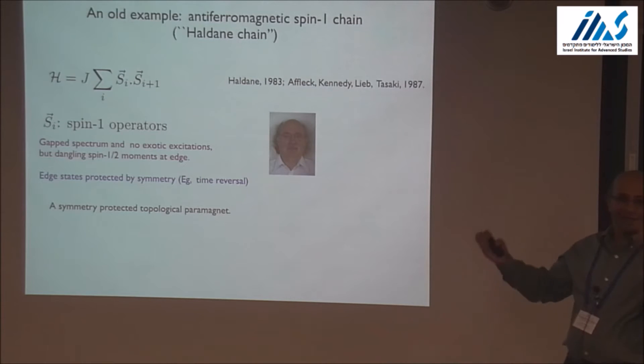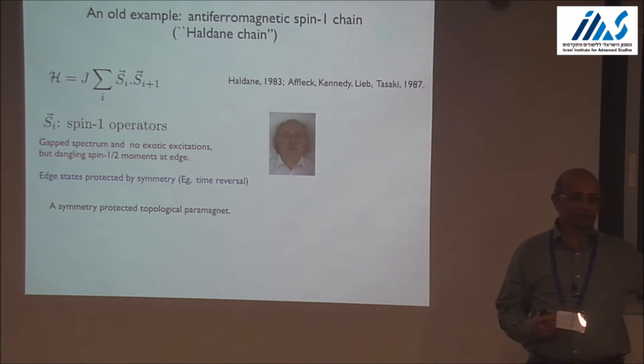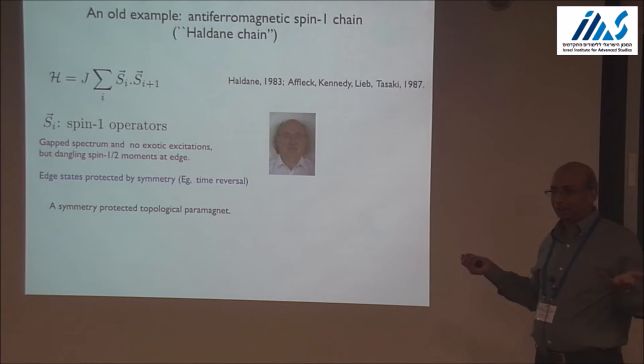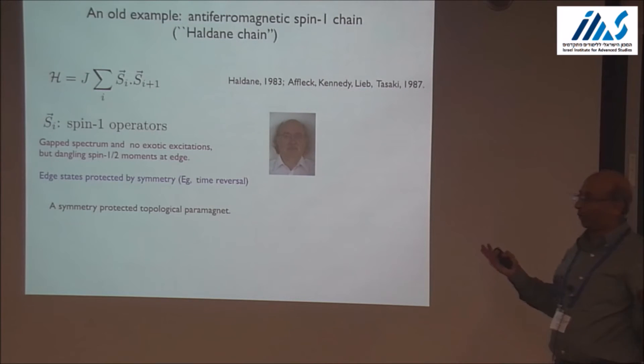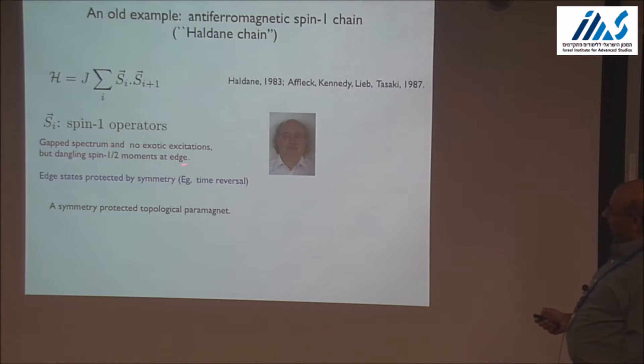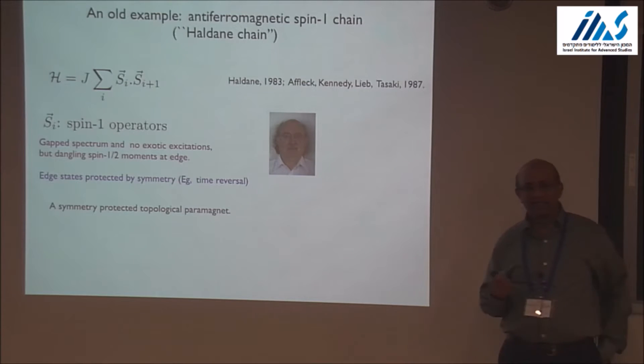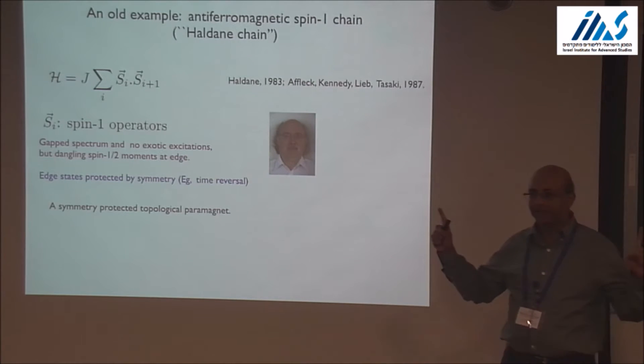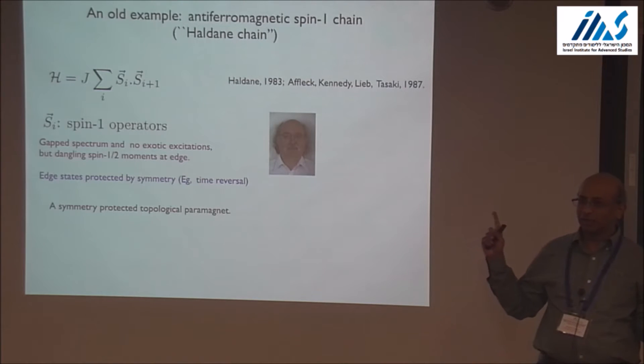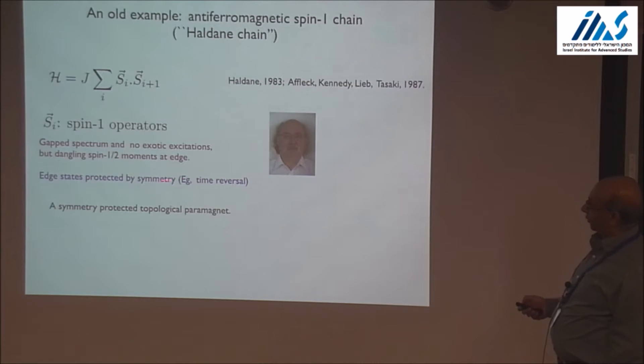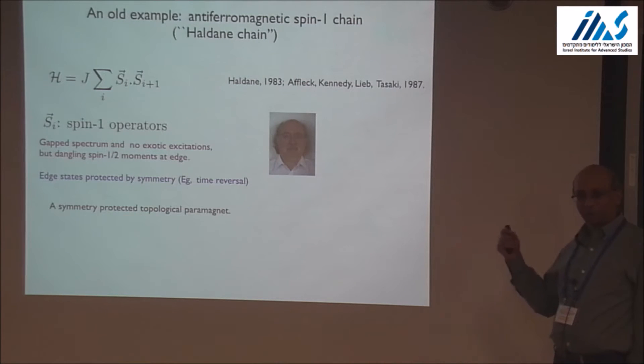It's pretty amazing that it can happen at all, and it happens without there being any gauge fields. That kind of phenomenon you saw happen in the fractional quantum Hall effect, but here it's a lot simpler than any of that. There's nothing fancy going on, yet the system does something weird. This is an example of an SPT phase. The non-triviality of the edge state is protected by symmetry. For instance, if you apply a Zeeman field — a magnetic field — it will spin-polarize the edge spins, and there's nothing interesting left at the edge anymore. The edge is non-trivial only so long as some symmetry, in this case time reversal, is preserved. This is perhaps the first example of a symmetry protected topological phase, and the topological insulators and topological superconductors are later examples that came two decades after.